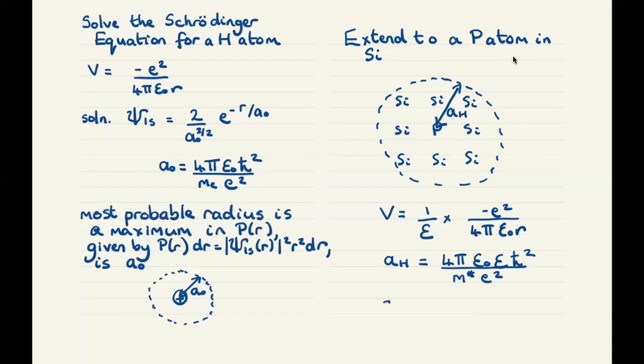And our lowest energy state, I'll put psi 1s in quotes because it's not exactly a 1s orbital of hydrogen, is now 2 over the hydrogenic radius to the 3 over 2 e to the minus r over a sub h. So that's the real space picture for our electron that's introduced into the silicon lattice by the phosphorus doping.